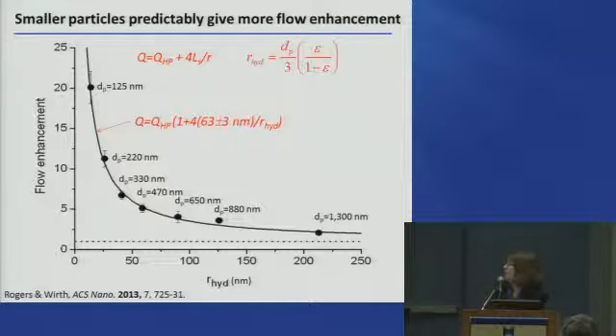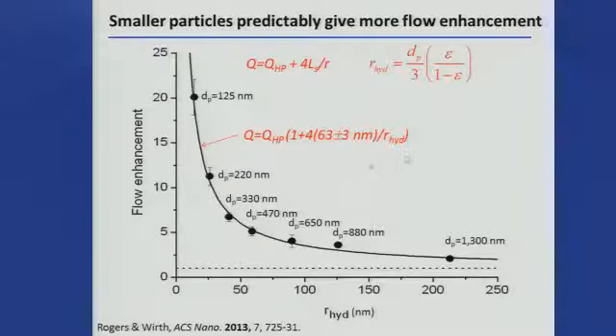And so this is a plot of flow enhancement versus the hydraulic radius between the particles. And so this is something that just comes from old fluid mechanics. If you take the particle size and you know the porosity, you can get the effective pore size in the medium. And then we use Navier's old equation from 1823 and constant slip distance. And so we can fit this, and it fits very nicely. So this curve is actually a fit to this equation with a slip length of 63 plus or minus 3 nanometers, from the 3 nanometer error coming from the regression. And so this illustrates that a packed bed obeys this equation that was derived for capillaries.